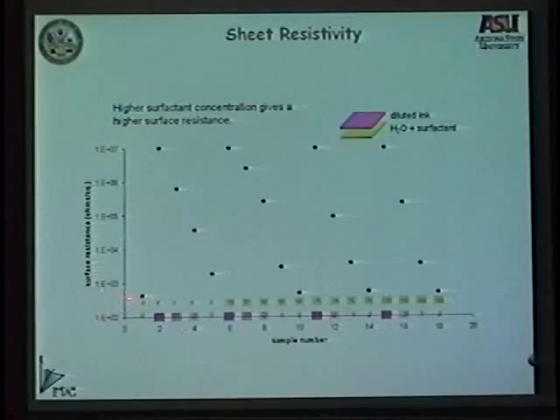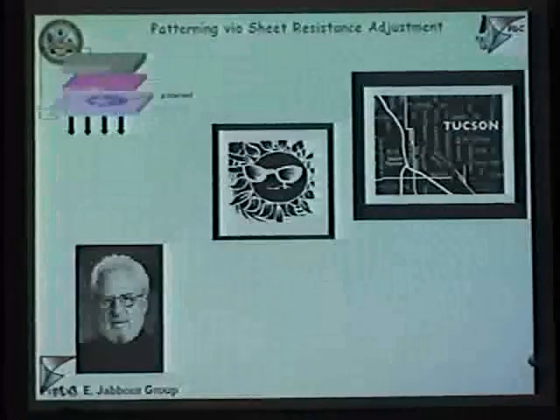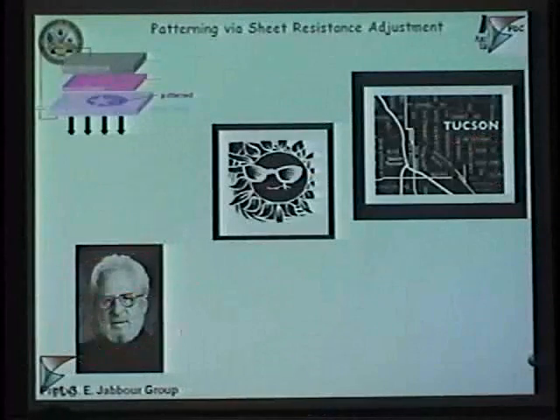We can go from this, and every time we print any of these points, or the points I'm not showing either because there's millions of these things, we also print this point here just for reproduction, just to make sure that the processing is not giving us the result. It is really the printing process that's allowing us to change this sheet resistivity in a linear scale, as you can see here. So you can take, for example, these maps and a photo of Professor Alan Heeger, who was one of the Nobel Prize winners for conducting polymers in 2000, and then you could print these with oxidizers on top of the substrate, wash it out, and this is what you should see if it works.